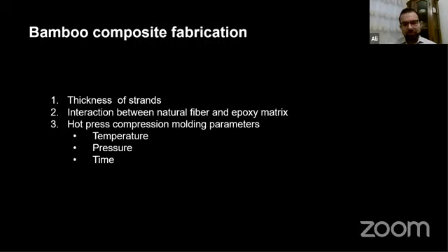The next step was to process the bamboo into strands. To do so, we used the machineries that were being used in many countries around the globe, but we modified them in terms of how we can get these strands into the right shape, right thickness, and with the right fiber diameters. The next step was how to interact the bamboo fiber with the resin matrix. And finally, we used a hot press compression molding system to compress all these impregnated layers together. The combination of the temperature of the hot press, the pressure of the hot press, and the time was very important. These 3 stages, as you can see, took us almost 2.5 years to reach the final product that had the properties that we wanted.